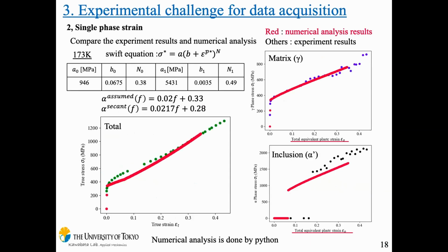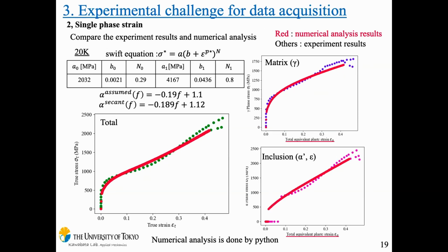Okay, and this is the result of the single phase constitutive equation. Using this single phase constitutive equation, we can get the overall stress and strain result; we solve the secant method using Python code. And yes, I think it's in good agreement with the experiment. And this is the result at 20 Kelvin. It's also in good agreement with the experiment result.